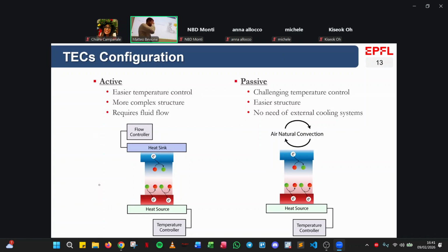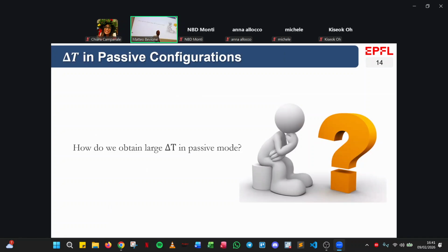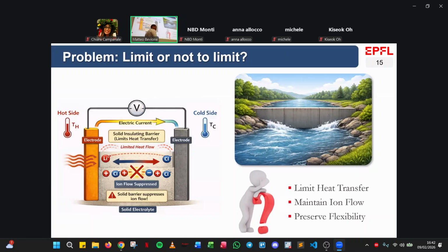But I faced a first problem, which is if you don't control the cold side temperature, then you will never get a very high temperature gradient, at least not in liquid cells, because the transport of heat throughout the electrolyte will be too fast. So the performance of these devices will be low. The first thing we can think about doing is maybe instead of using a liquid cell, we can use a solid electrolyte, but that wouldn't work because you are preventing the flux of ions, or anyway, you are not any more flexible as we want it to be.